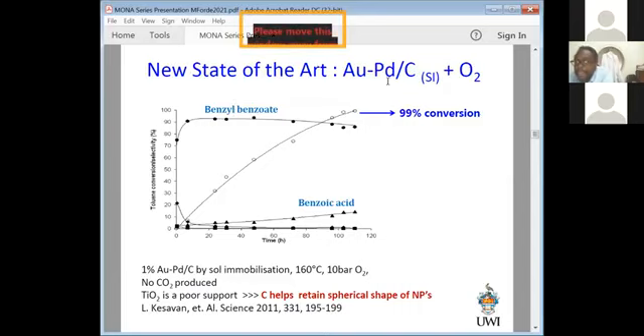So this is not a desirable product per se, but of course you could do hydrolysis on it at the end if you wanted. The interesting part is that only catalysts prepared on carbon showed this sort of activity-selectivity relationship. At the bottom of the slide, you'll see that TiO2 is a poor support for this. In the work I was doing at the time, I couldn't use carbon, because every time I put the metals on carbon and put it in the furnace to heat it up during the synthesis, because the particles are so small, in the presence of any oxygen at all it burns the carbon and decomposes it. And he's published this in Science, so maybe I wanted to try it and see what I could get.